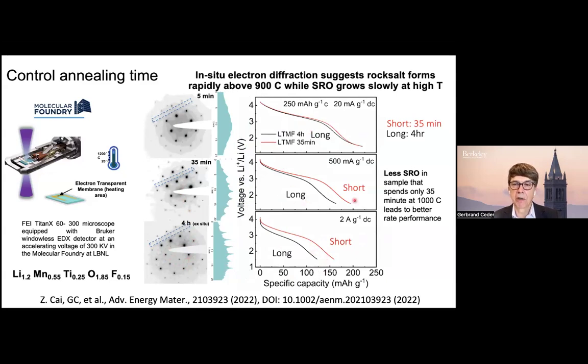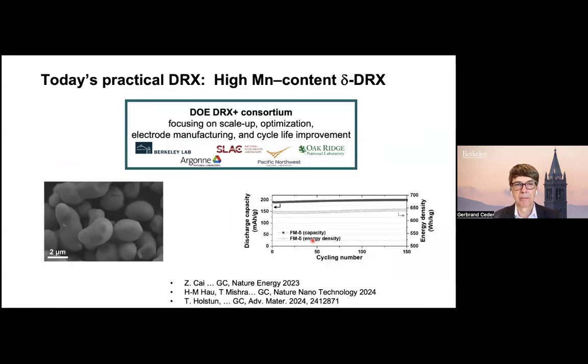Long means long annealed, short means short annealed, at different rates. At low rate, you barely see any difference, but at high rate, you actually see quite a difference. And so again, because in the short anneal you have minimal short-range order, you have better transport characteristics.